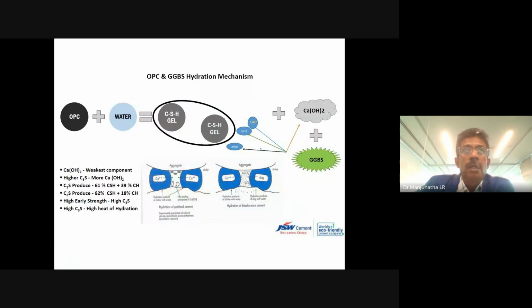So not only is it reactive, this is double reactive. The reason is, when you add water to OPC 43 or 53 grade, you get two components. One is the CSH gel formation and the other is calcium hydroxide. Calcium hydroxide is about 26% present in the concrete body. Then about 50-55% we get CSH gel, and the balance is the ettringite. So what we have to do now is convert this calcium hydroxide into a more useful product called CSH gel. The more CSH gel, the more particle packing will happen in the concrete.